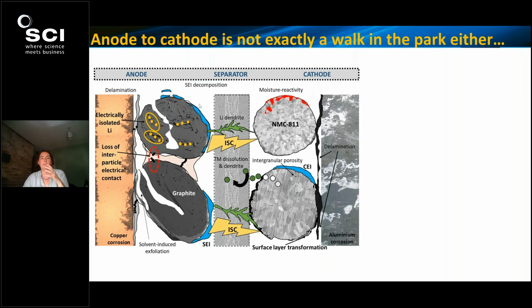They can have porosity in the electrode that blocks up and so makes it so much more tortuous for the lithium ions to move. And this is before we even get to the cathode, which, as we saw earlier, has its own set of tortuosity and degradation and aging mechanisms, as well as corrosion of its own current collector. And so this also is a treacherous journey for lithium ions.